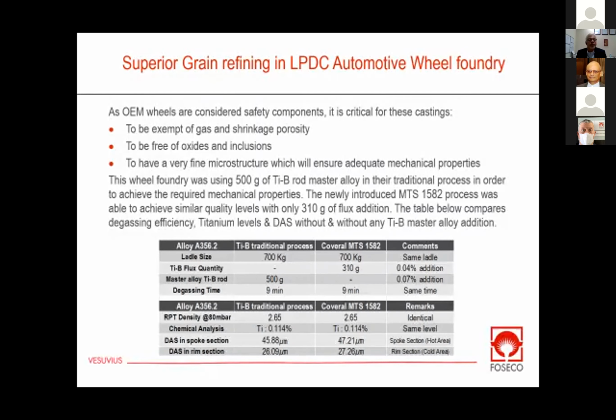This is an Asian automotive wheel foundry, a very large group with many foundries and many low pressure machines. Their traditional process, with parameters summarized here, used a 700 kilo ladle in which they added 500 grams of master alloy, then did a 9-minute rotary degassing treatment before transferring this A356 alloy into their furnace.